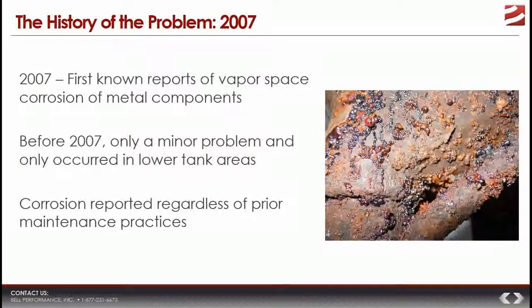So you have vapor space corrosion, where internal metal components in those tanks above the fuel line are experiencing significant corrosion damage. And so these are areas above the fuel line, which means they're not in regions submerged in the fuel. And that is a key distinction, because prior to 2007, storage tank corrosion was considered a minor problem. And when it did occur, it really only occurred in the lower, what they call the wetted portion of the tank. So now, 2007, there is a new and troubling trend that the industry is starting to see.